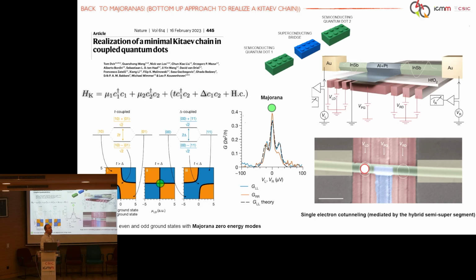So have Majoranas been discovered or measured, or whatever you want to put it? Yes, for sure. In these minimal Kitaev chains, there is exquisite control of the properties of these tiny devices, and this is, again, an indium antimonide nanowire. This is quantum dot 1, this was my green block. This is quantum dot 2, my second green block, and this blue is the superconducting bridge. Indeed, they can tune the system to have this condition, and when the single electron tunneling is equally probable to the Cooper pair splitting, you have a very clear peak at 0 voltage. When you don't reach this condition, you don't see this peak. So you can create at will Majorana zero modes in this minimal Kitaev chain. It is not a topological chain, answering your good question. So this is a minimal chain.